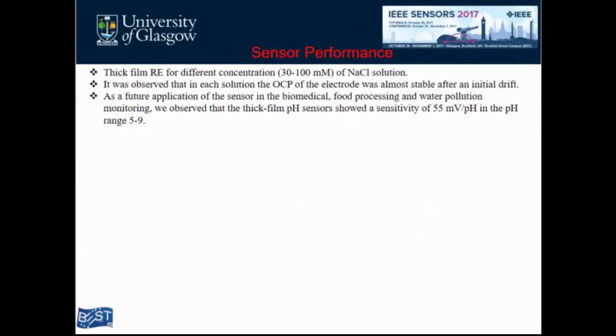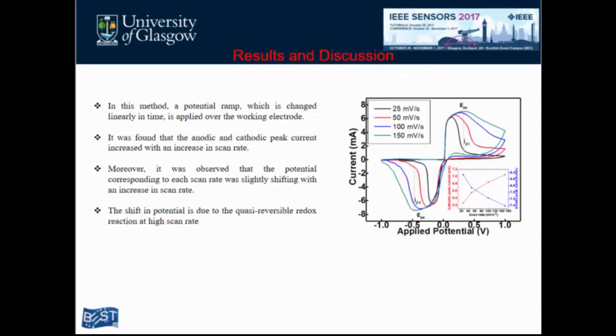After that, the basic study of cyclic voltammetric analysis. Here you can see the applied potential against the measured current in cyclic voltammetry, with different scan rates. It seems that even with a high scan rate the reference electrode is working perfectly, and the anodic and cathodic peak currents show that it is a diffusion controlled reaction.